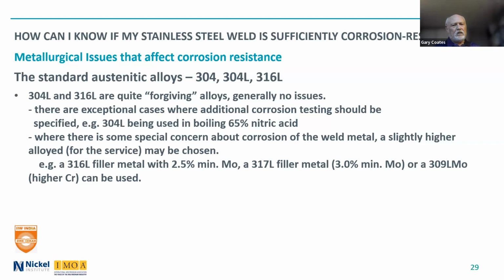And now, can you use, there are some cases where you may want to use a slightly higher corrosion-resistant filler metal for a particular service. It might especially be when you're doing repair welds. You might want to use on 316L a filler metal with 2.5% min moly rather than the 2.0, which you are almost guaranteed to get in the parent material. I've been involved in pulp and paper mills that will use 317L that is very similar to 316L, but has 1% more minimum molybdenum in it, or even the 309LMo filler metal, which has a higher chromium, same moly content as 316L. Those are all suitable for welding 316L, where you're really concerned that you want the weld to be higher corrosion resistant.